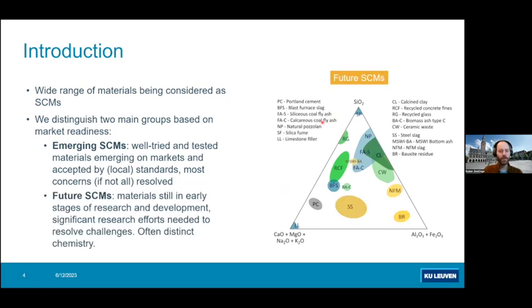But that's not all. Obviously, there are many more materials being explored, and many of these materials are still in fairly early stages of R&D, and there's still quite a few remaining efforts to be done. And if we plot them on these ternary diagrams, we can see that they often have slightly distinct chemistries. For instance, plotting more towards iron-rich or alumina and iron-rich systems.